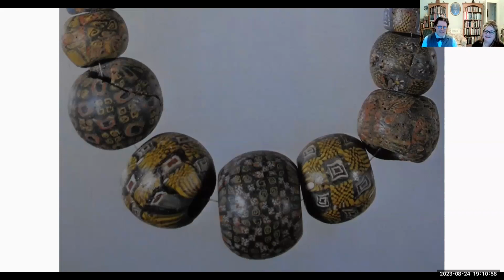Yeah. And the last thing, which again was probably less of an issue for the Vikings because they probably weren't working in a well-insulated, not so well-ventilated building, was toxic fumes. Because to give glass different colours, you put different chemicals into it. And as you heat it back up, these chemicals give off gases, and some of them aren't terribly pleasant. So I work with a vent system, much like the hood over your oven in your kitchen, so it's constantly pulling fumes away. If the Vikings were working outside, they didn't have that issue.